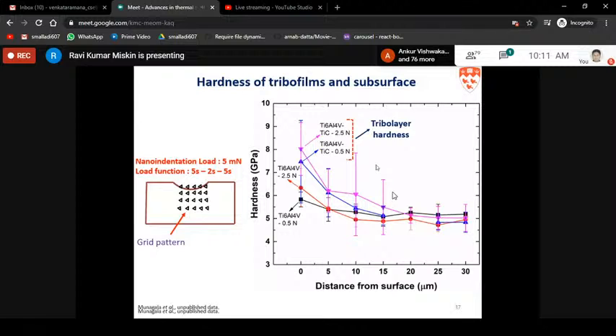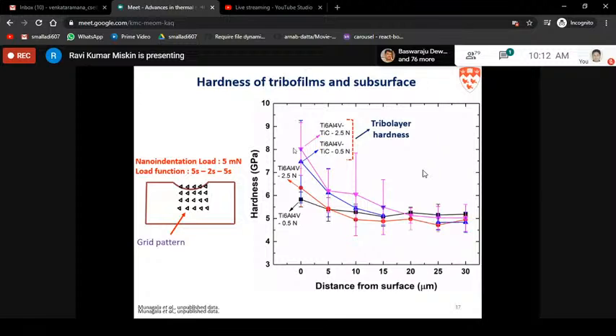But in case of titanium 64, there's a blue fellow down there. Titanium 64, the red and the blue guys, your hardness is very less. So sorry, red and black. So the titanium 64, your hardness is very less. So when you have tribolayer formation in composite, basically you are having very high strength at the surface. You wear less, but when you don't form tribolayers, basically you actually wear out faster.